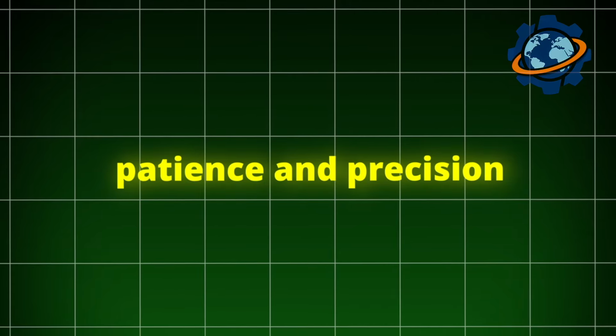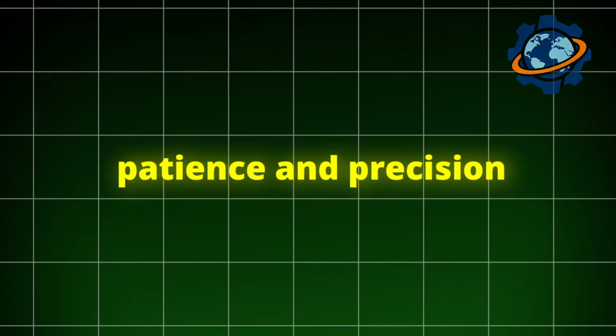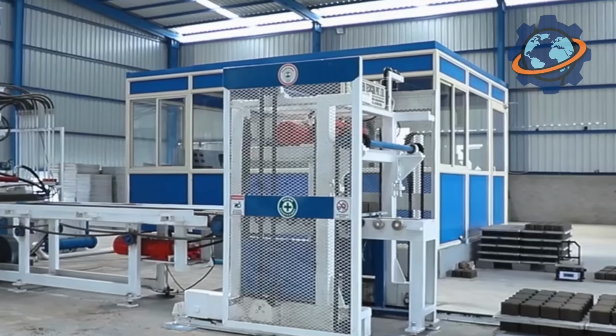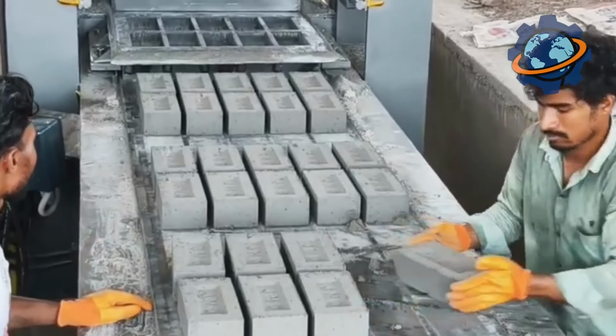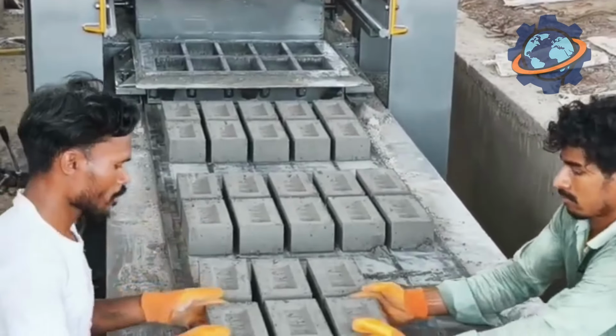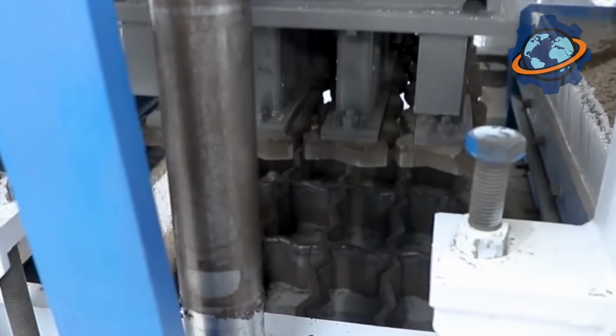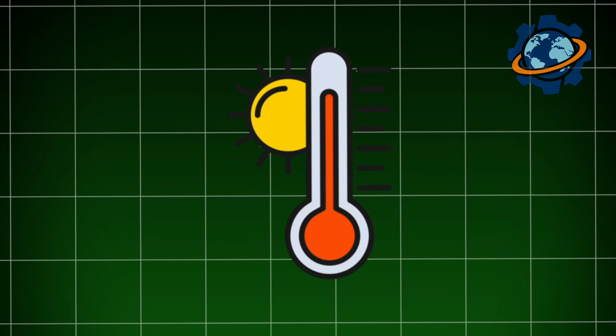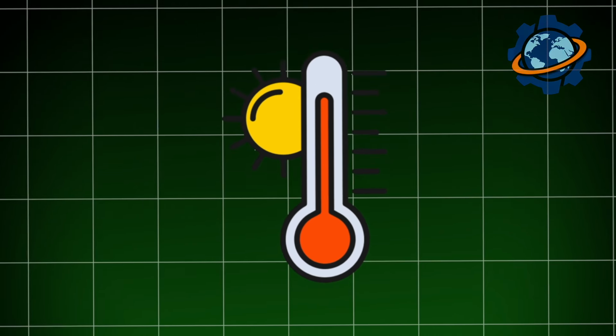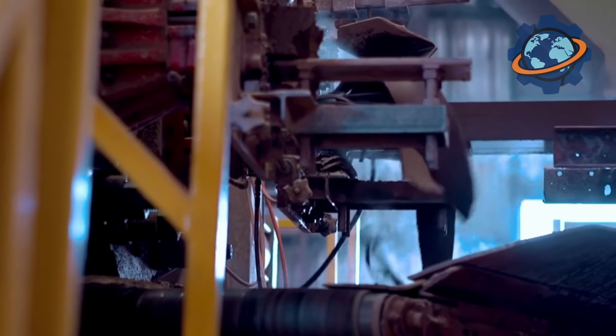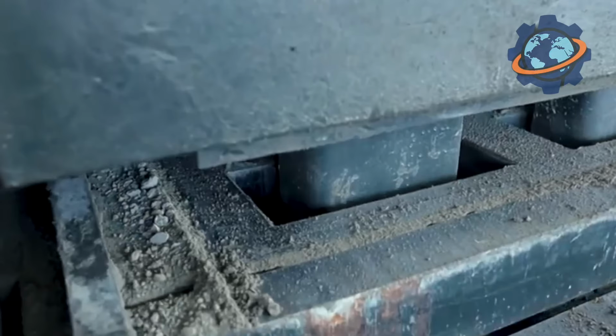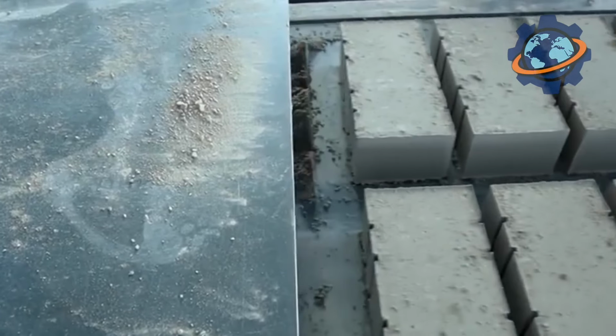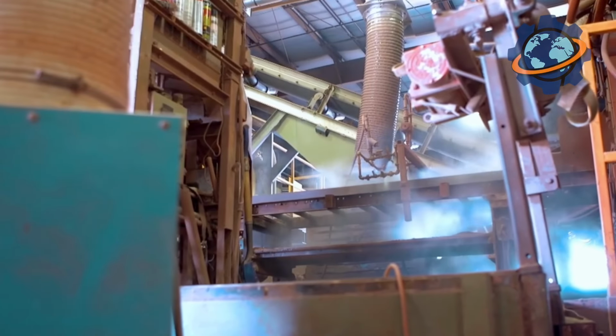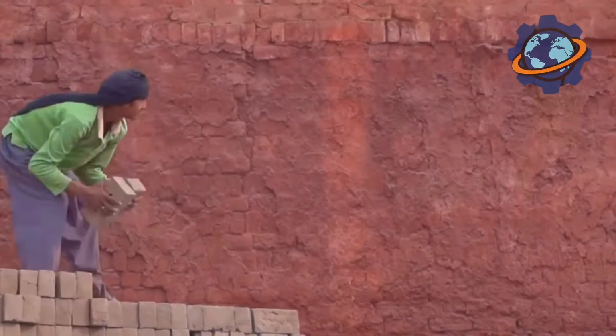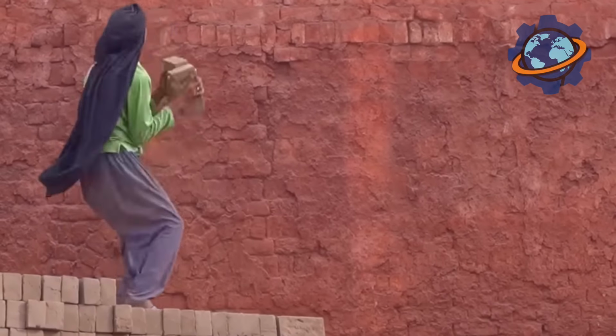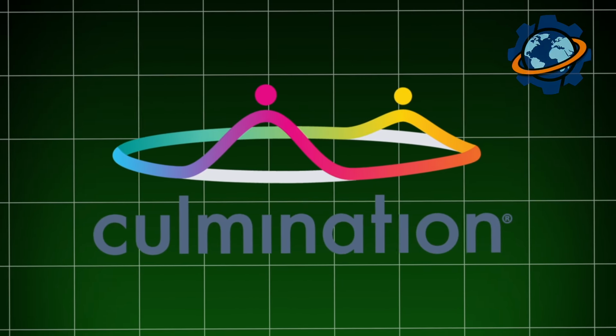The next stage requires not strength, but patience and precision. The green bricks are carefully placed on kiln cars and sent to long tunnel dryers. This is a slow and delicate stage, which can last from 1 to several days. Inside the dryer, a carefully controlled microclimate is maintained. The temperature is gradually increased, and the humidity is reduced. It is important that the moisture leaves the brick as evenly as possible from its entire thickness. Any rush or violation of the regime will lead to the outer layers drying faster than the inner ones, which will create critical internal stresses and simply tear the brick apart with cracks from the inside. When all the physically bound water is removed, the culmination of the entire production cycle begins: firing.